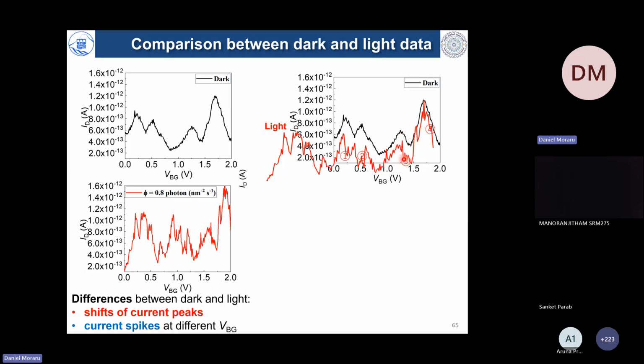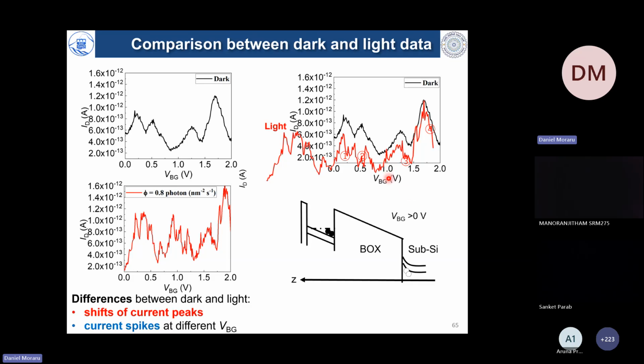What changes this VBG effective scale is the fact that most of the photons coming from the left side pass through the oxide, pass through the silicon layer, pass through the box layer, and get absorbed mostly in the substrate. So this modifies the backgate voltage effectively. This is an important effect.